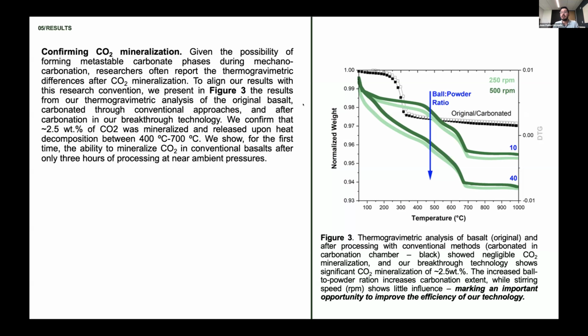And that makes sense because we need mineral dissolution to actually induce carbonation, which is exactly what the green curves show you. Particularly, they show that ball to powder ratio turns out to be a key variable, controlling how much carbonate we can form in mechanical carbonation. We form about 2.5 weight% of carbonates in basalt in just 3 hours, which marks an opportunity in our technology: not only can we carbonate, but we can improve the efficiency of carbonation if we change and control the variables that I mentioned before: milling energy, ball to powder ratio, liquid to solid ratio.